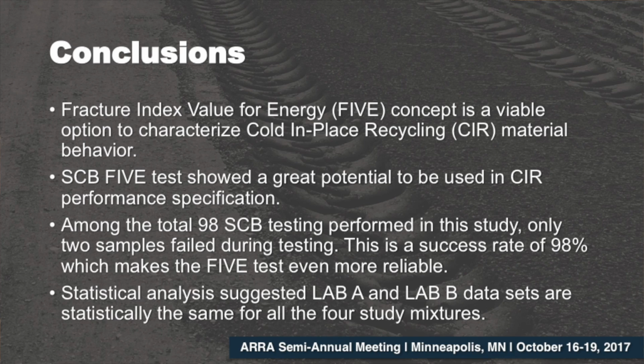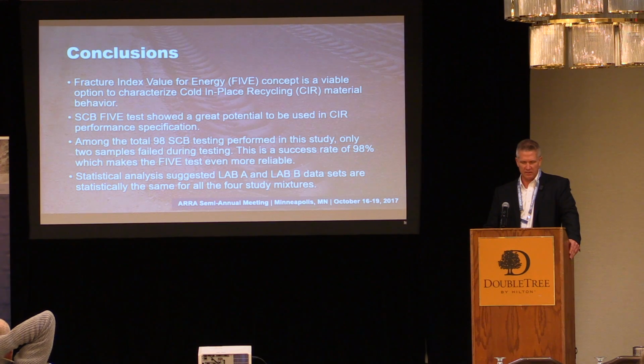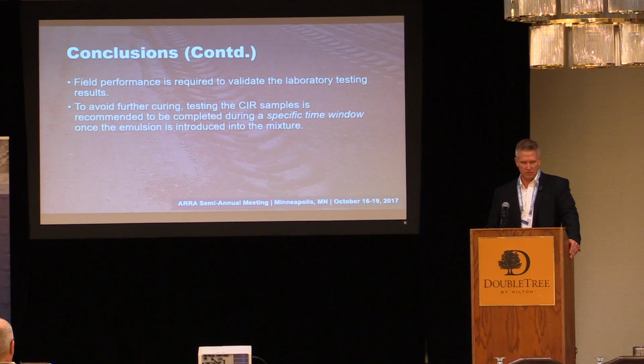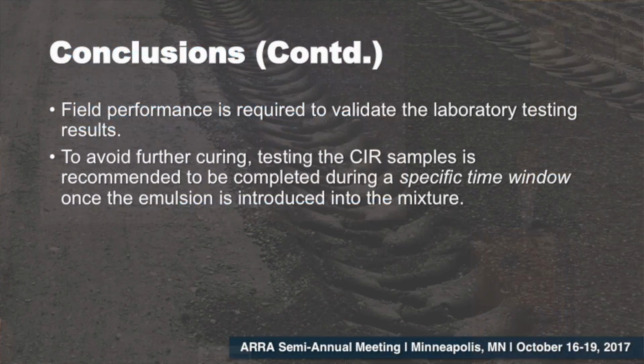And the statistical analysis suggested that the data sets are statistically the same for all the 4 study mixtures. So fracture energy certainly is showing that it's a viable alternative to not only look at crack resistance, but it's also potentially going to provide a means to advance into the quality control, quality assurance, which I think Brian's going to talk about further. Field performance is required to validate the laboratory testing.